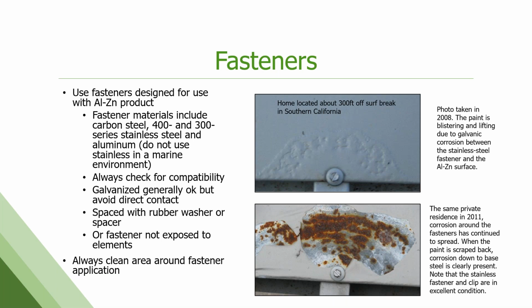I have a picture here. This is a private home, about 300 feet off the surf break in Southern California. The picture on the top was taken in 2008. This complaint came into us as the paint blistering and failing. Well, the reason the paint's coming off is because of the corrosion occurring on the substrate underneath. That fastener and that clip coming down from it, which is holding a stainless steel gutter up along this roof, all stainless steel. So the panel here, the aluminum zinc panel, is sacrificing itself to the stainless.